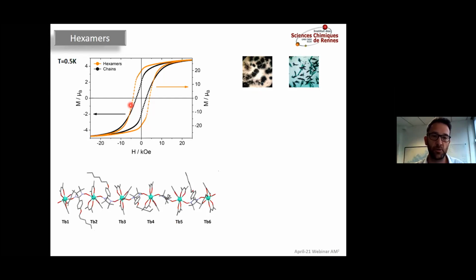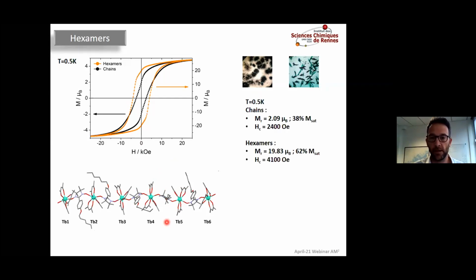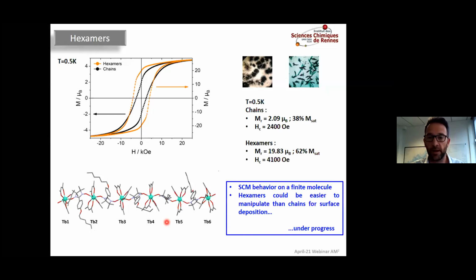We cannot extract precise coupling values because we have a lot of different terbiums. We have a lot of different radicals, and on these chains we also have radical-radical interaction and terbium-terbium interaction that are actually bigger than the terbium-radical interaction. These are called next nearest neighbor interactions. So it makes those things very, very complicated, and we are not able to extract very precise values on this kind of system. But anyway, we have been able to observe the single chain magnet behavior on finite molecules.